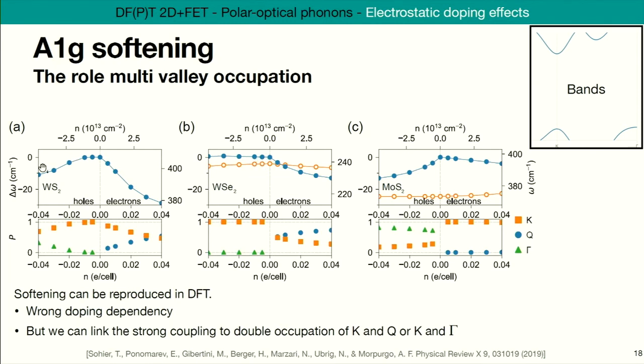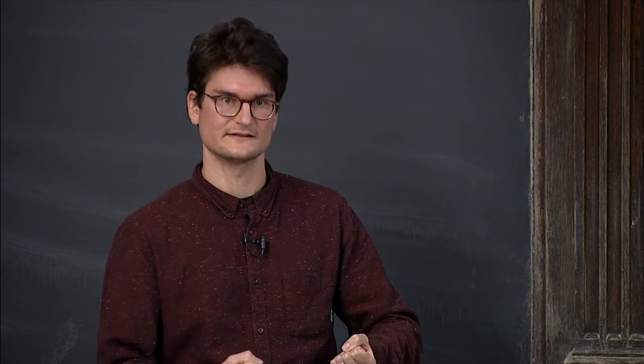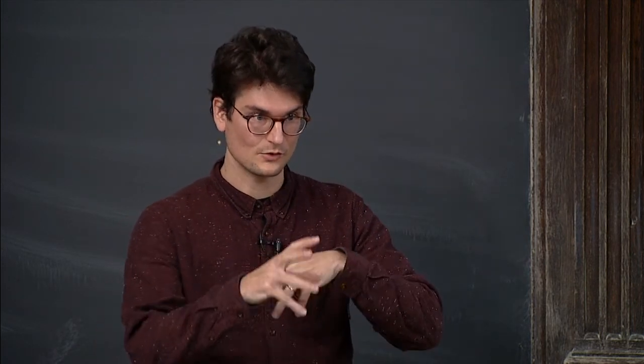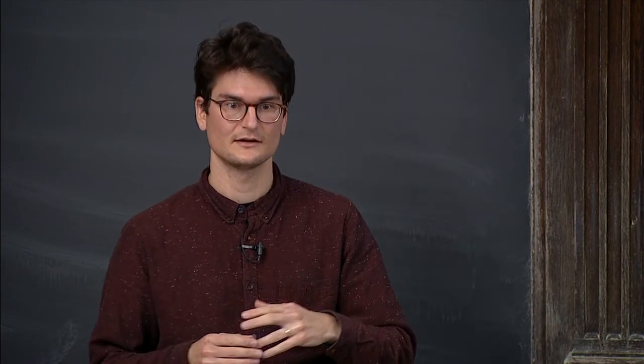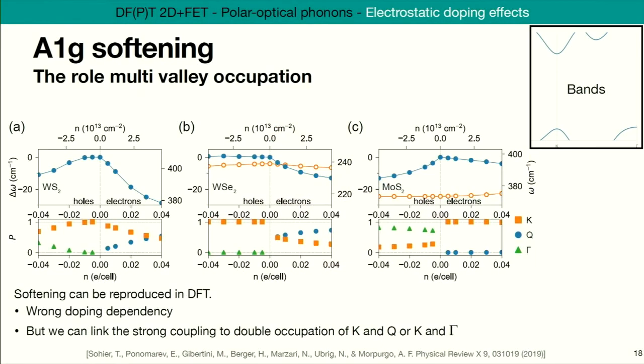But sometimes it softened for both, and sometimes even for just holes and not electrons. So very confusing. We got very confused for several weeks about this. The only good thing here is that this is DFT, so we can go and look at different parameters and try to plot out things and really understand what's happening relatively easily, more easily than experiments at least. So we managed to correlate the softening with double occupation of two valleys.